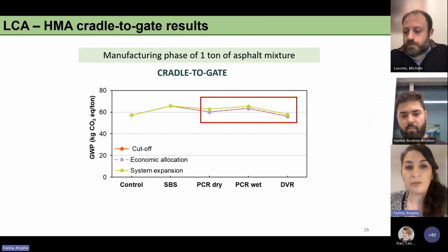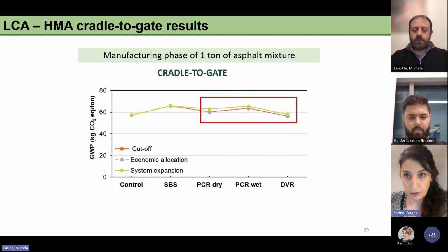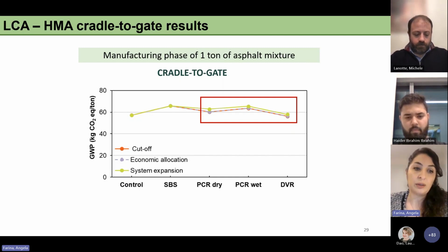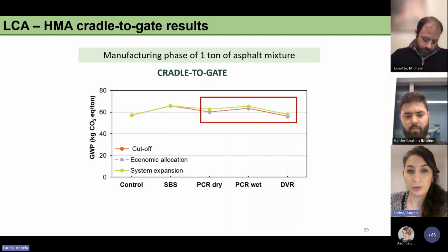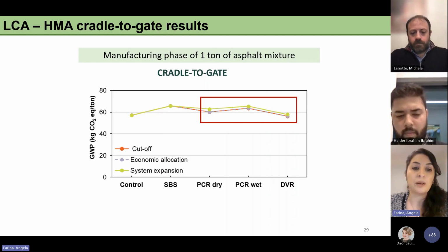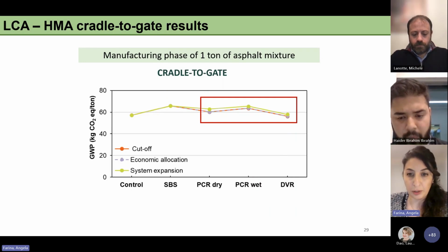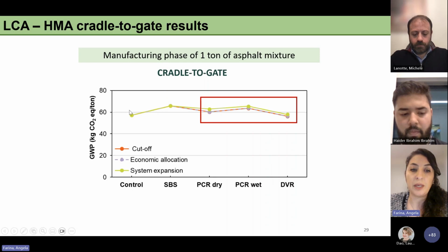And also these results can be reflected on the life cycle assessment results for 1 ton of asphalt mixture. So this graph is showing the global warming potential of the cradle-to-gate analysis for the asphalt mixtures based on different allocation methods applied to the crumb rubber. And the control, so the unmodified asphalt mixture, is the mix with the lowest global warming potential, and the SBS is the one with the highest carbon footprint, and the asphalt mixtures with the scrap tires are in between.